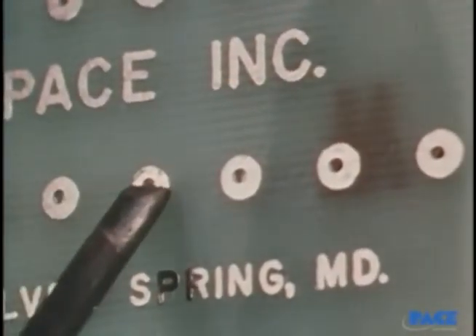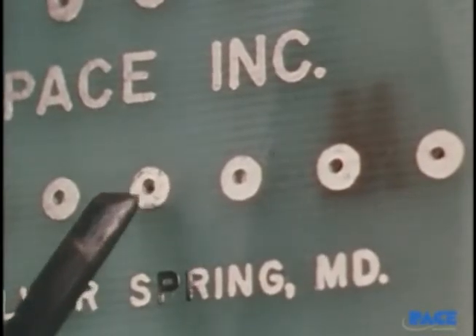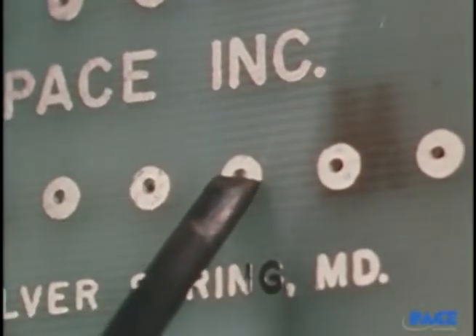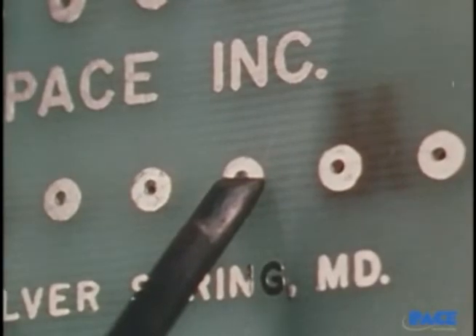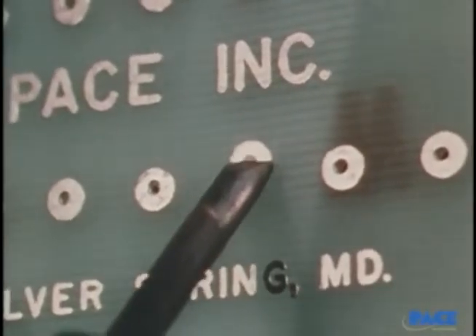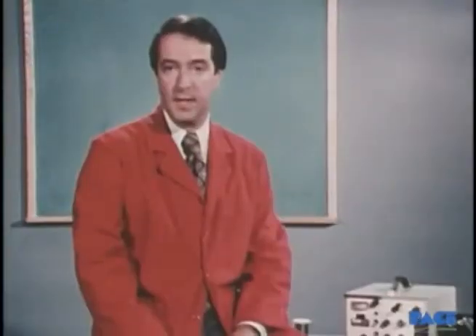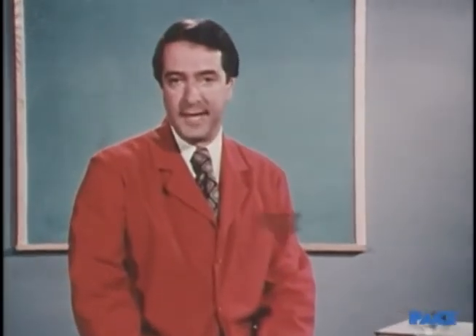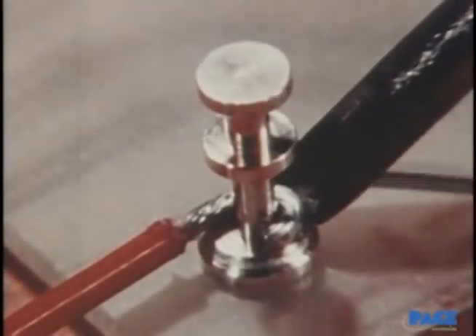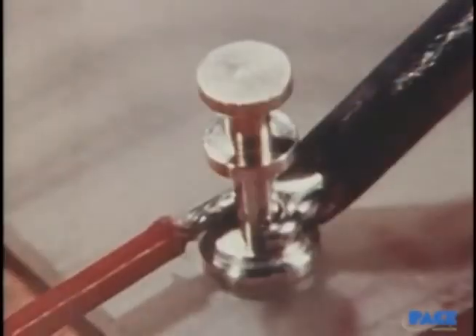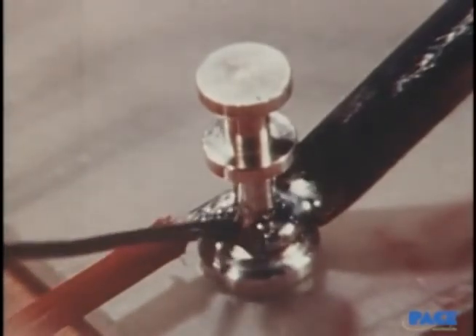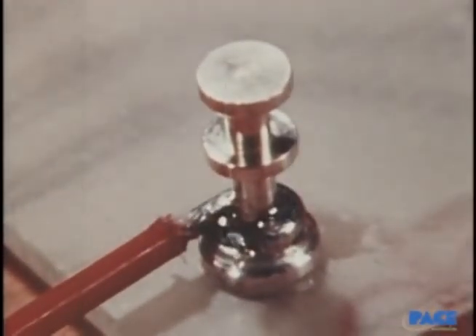In practice, remember to use a light touch. No more pressure than you'd get from the weight of a pencil balanced on its point. Push down on it like this, and you may lose the pad. A general rule for preventing overheating is to get in and get out as fast as you can. That means using the hottest iron you can react to, one that gives you a 1 to 2 second dwell time on the particular joint you're soldering. In the next part of the program, we're going to take up turret terminals and begin to apply what we now know about high reliability soldering.